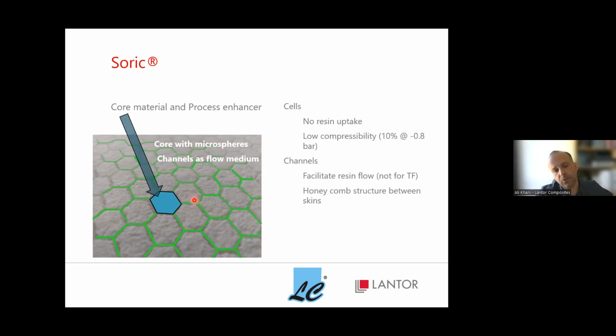So basically this Soric has two parts. It has these cells or islands, and it has these channels around it. So these cells, they don't have resin uptake, or they have a very little amount of resin uptake because they are full with the microspheres. And they have low compressibility. So basically under vacuum, they may lose about 10% of their thickness. And then you have the channels, which help for resin flow. And also after the laminate is cured, you would have a honeycomb structure between the skins because the resin has filled in these channels.